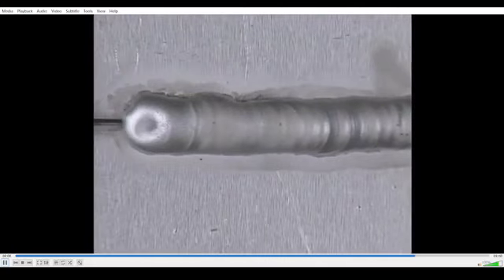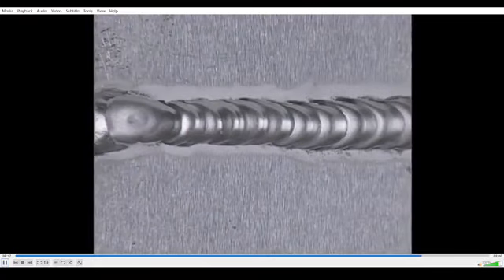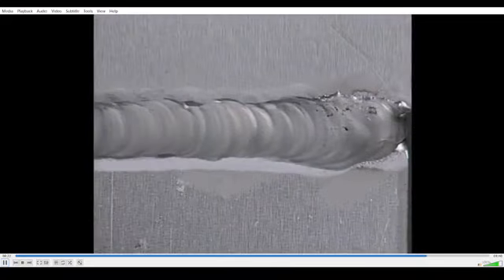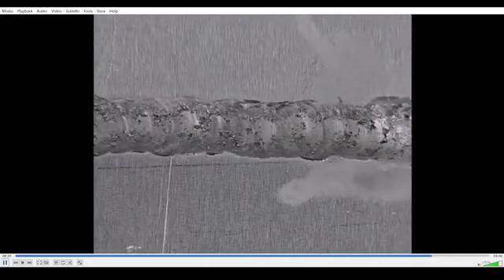Welding with the amperage too low or traveling too slow causes the weld metal to pile up, resulting in overlap and poor penetration. Traveling too fast produces a narrow, irregular weld with incomplete penetration into the root. Too long an arc length produces a wide, flat, irregular weld with incomplete penetration. A dark weld with porosity indicates insufficient shielding.